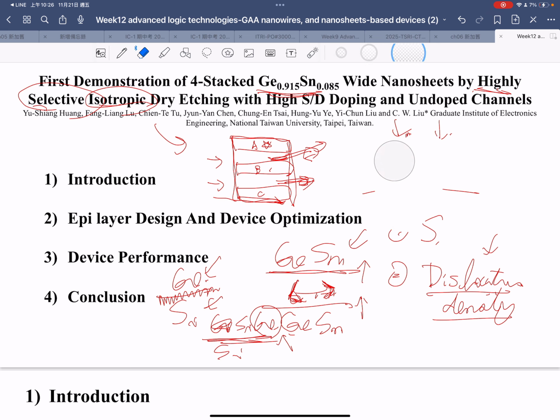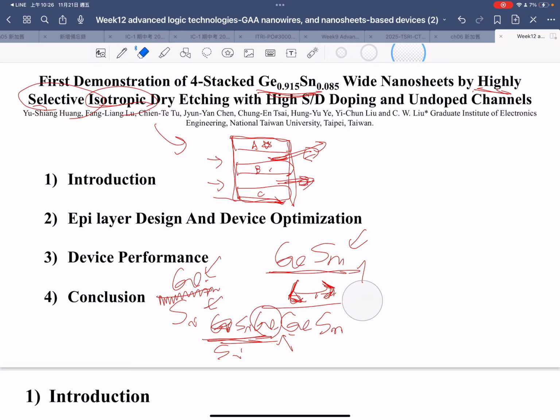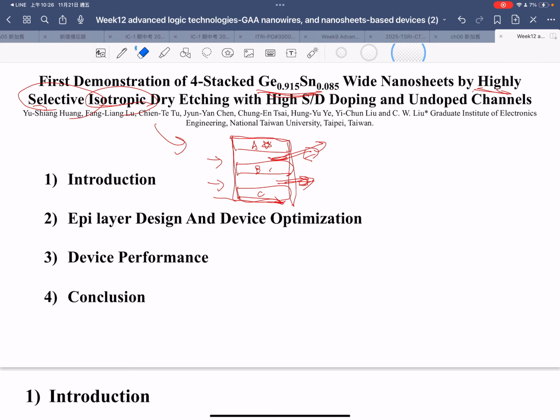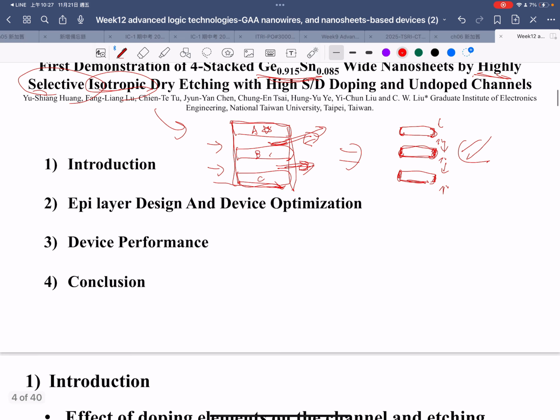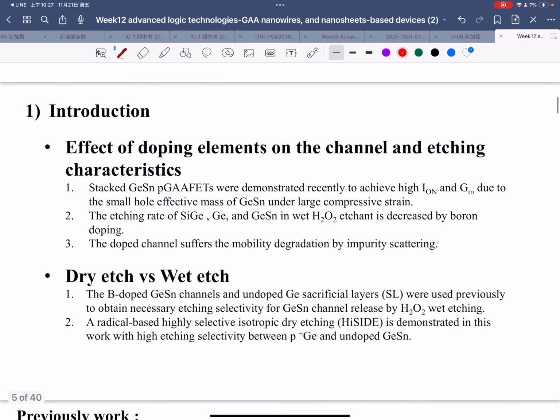So usually, if we have to take care of both etching selectivity and dislocation, you may consider a trade-off situation. So after etching, the width will become smaller, and we have a round corner. And it becomes smaller. So this is the trade-off between the etching selectivity and the dislocation density. Okay, so let's read this paper.